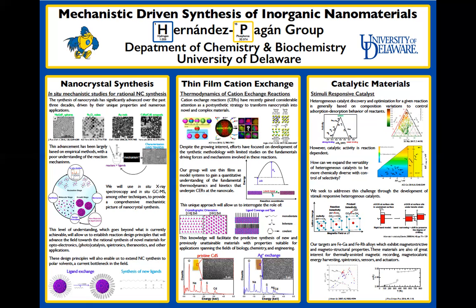And furthermore, these catalysts tend to be reaction dependent, right? So a catalyst that might be good for making hydrogen is not necessarily good for CO2 reduction. And so here in this middle image on the catalyst section, you can see the different metals that can produce hydrogen versus CO products versus different other carbon products, right? Like the case of copper, which is very unique. So the question then is, how can we improve the chemical diversity of these catalysts and control the selectivity for a given catalyst.